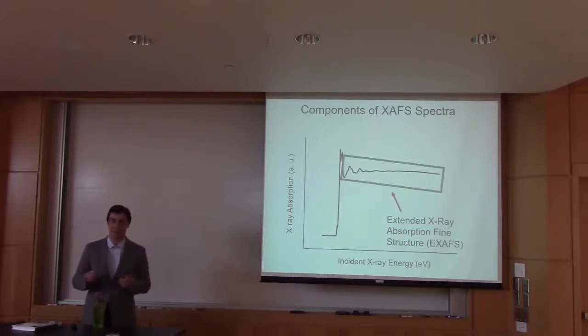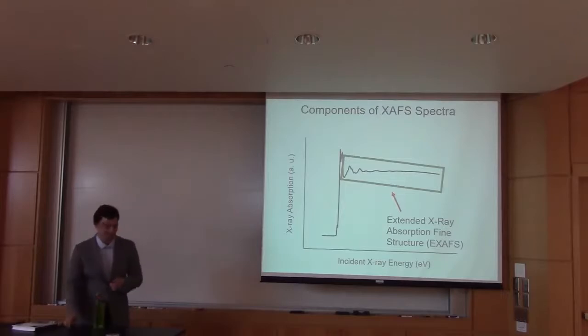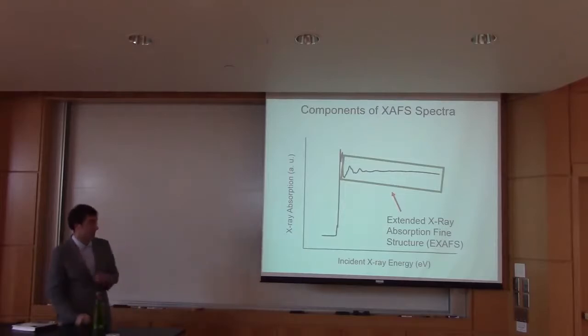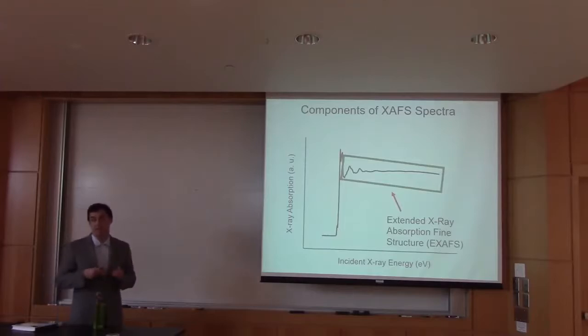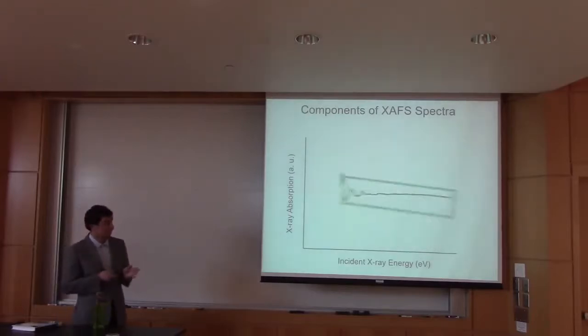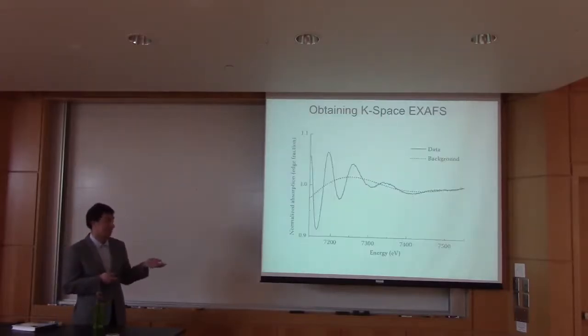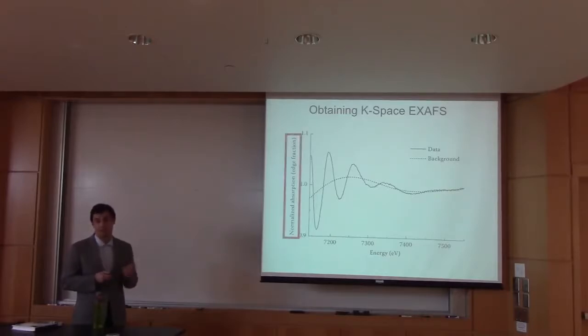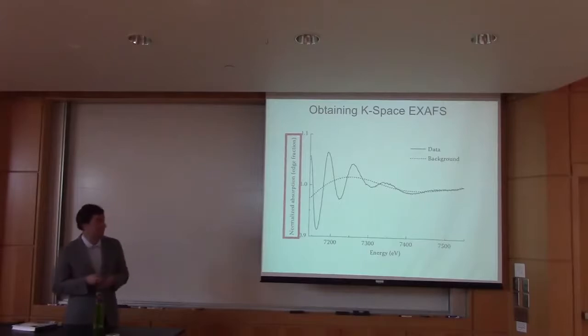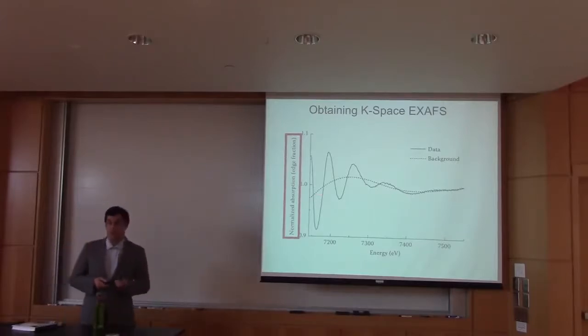So although it sounds like a lot, it was really easy to just click it and watch the new spectra pop up. So now I'm going to show a different plot, but it's just used to emphasize the next step. We're going to zoom in on the XAFS region, and then we're going to normalize the absorption, so it's the same across multiple spectra. We're then going to remove this background function, so we're just left with signal, and you'll probably have repeated these different experiments multiple times, and you'll average those together.